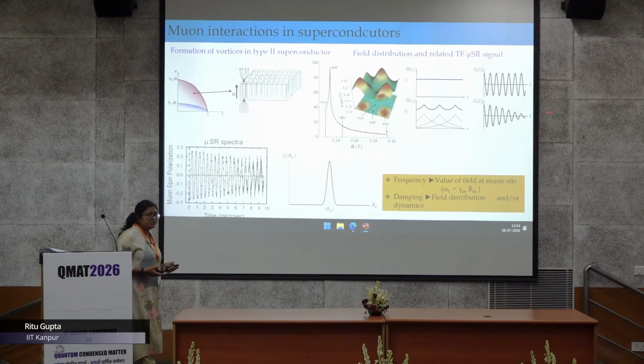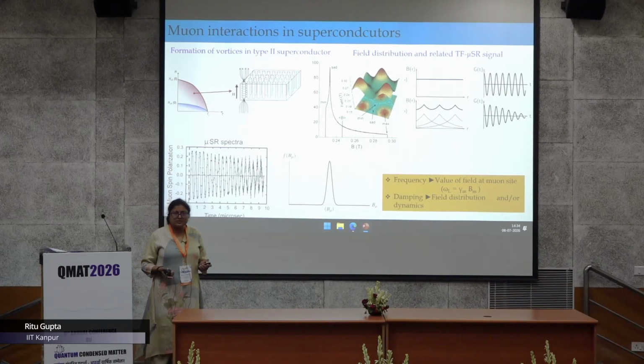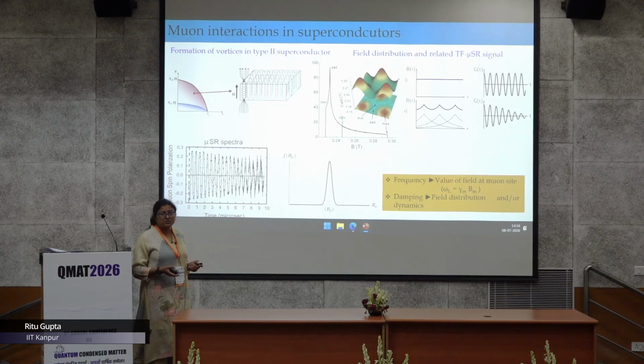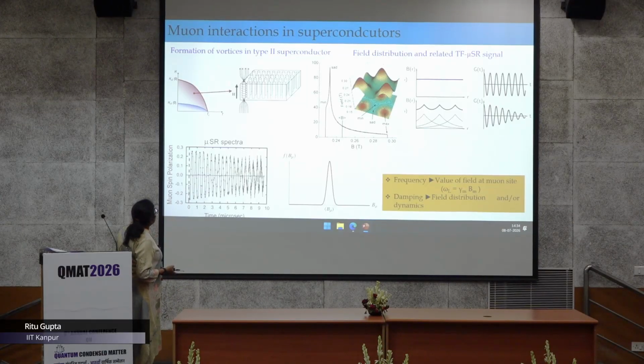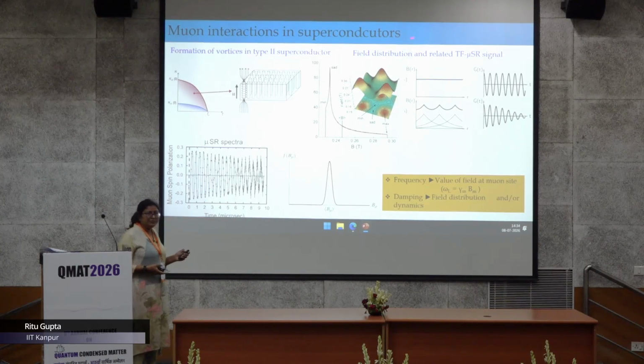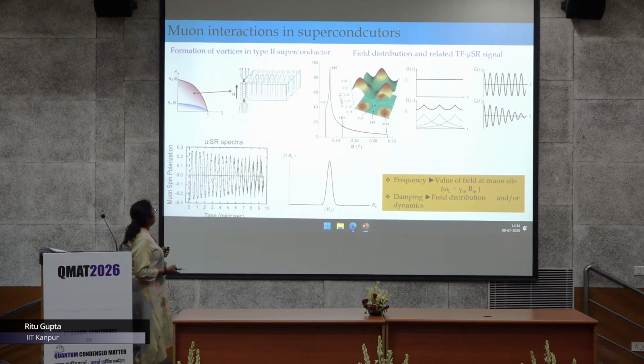Okay, so in the case of a superconductor, how is this technique important in determining the superconducting gap symmetry? I will be talking about type 2 superconductors. If we apply a field in the vortex state, that means between Hc1 and Hc2, the magnetic field will start penetrating through the material in the form of vortices. And if you look at the field distribution, this is how it should look. The peak shows the position of the vortices.